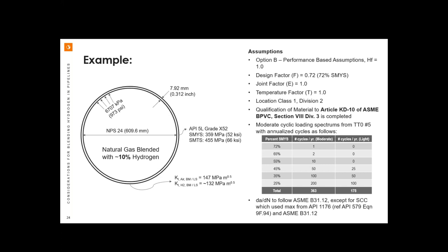And we'll also assume that we've gone ahead and qualified our material or have sufficient material records to show that we have the following material fracture toughness properties. So in air for base metal and long seam, and in hydrogen at a 10% blend rate, we lost about 10%. So we still have 90% left.